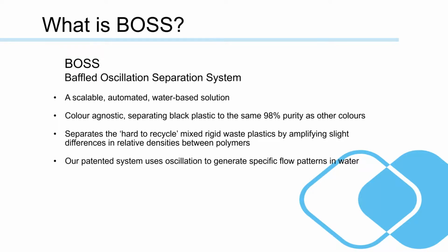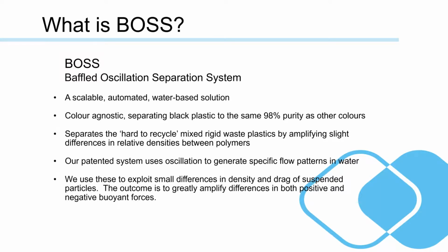The way this works in practice is as the stack oscillates up and down, it generates flow lines between the baffles, and these flow lines are generated by vortices. So as the stack oscillates up and down, you have vortex shedding, and the vortices affect the polypropylene in a different way to the polyethylene. It has the effect of increasing the residence time for particles of polypropylene and allowing us to wash out polyethylene particles. And it does this because the separation happens because of the difference in density, which is ultimately driving the buoyancy of the particle, but also in the drag profile of the suspended particles.